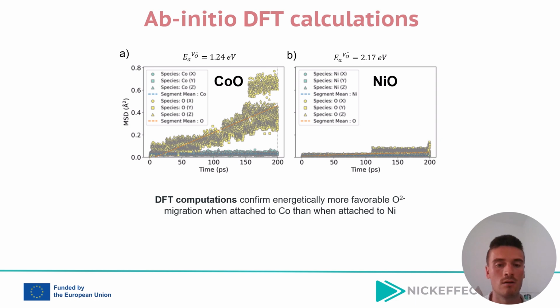The vacancy-induced mean square displacements of oxygen atoms, in cubic cobalt monoxide and nickel monoxide, were computed as a function of time using molecular dynamics, as reported in the panel of the slide, at a given temperature of 2000 K.